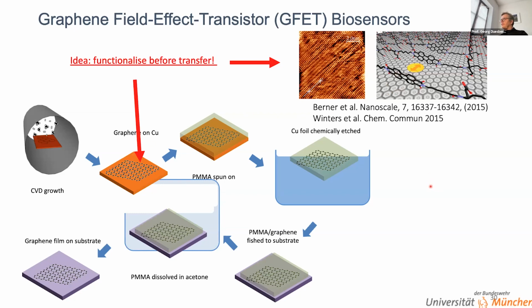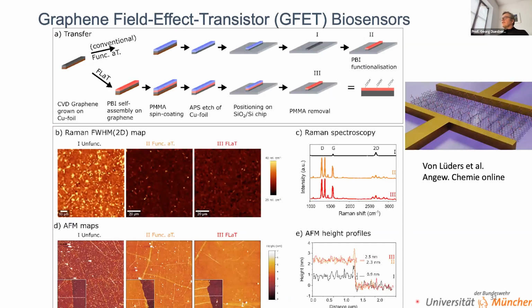This is PBI molecules to then do further functionalizing onto this PBI layer, which then sits on top. So our integration scheme for graphene, that would be the conventional way: we transfer graphene and strip it onto silicon and then functionalize it. We basically do the functionalization on copper first and then transfer the material onto silicon and then remove the layers, leaving it directly as a functionalized layer.